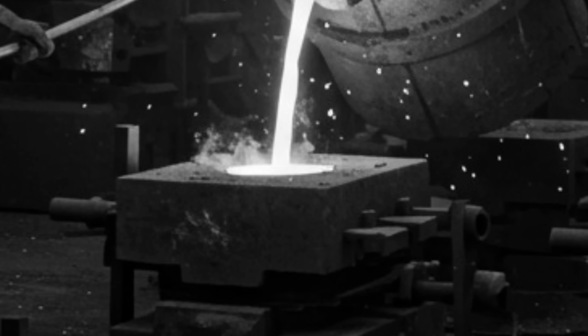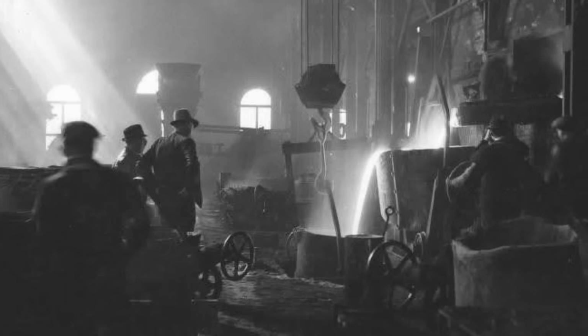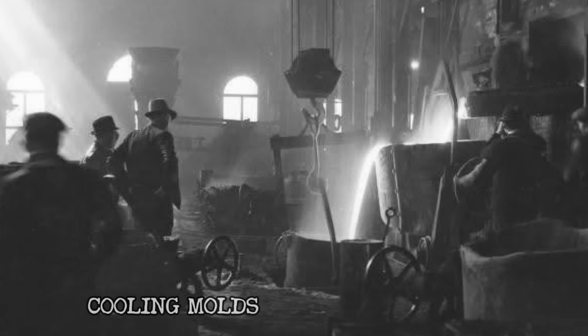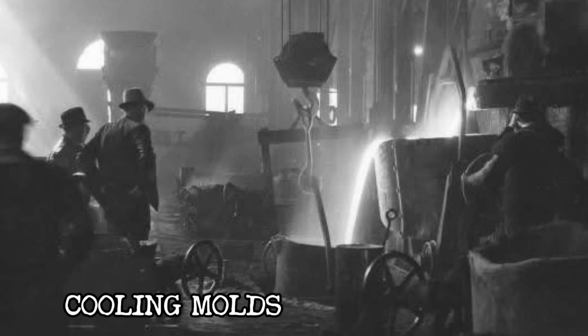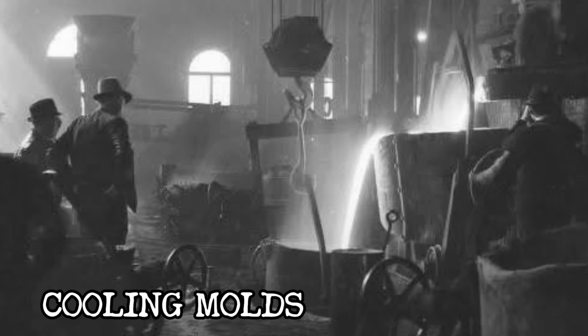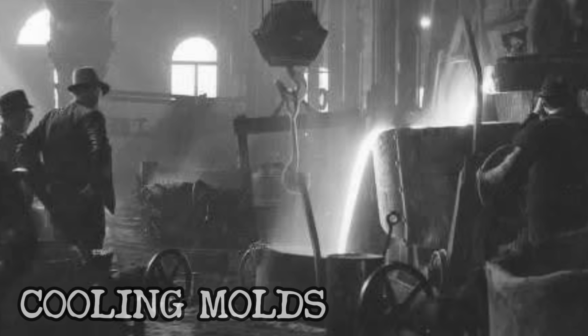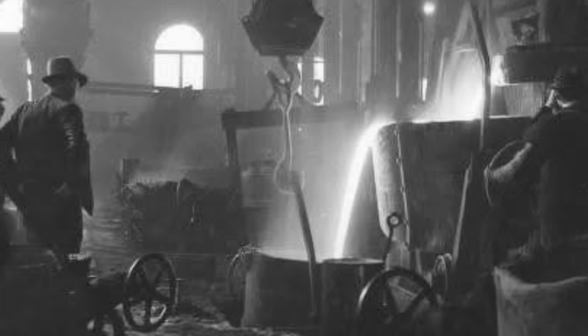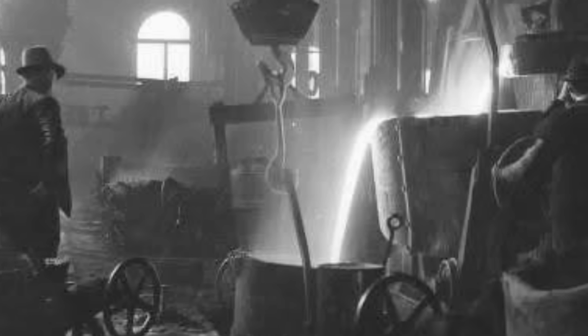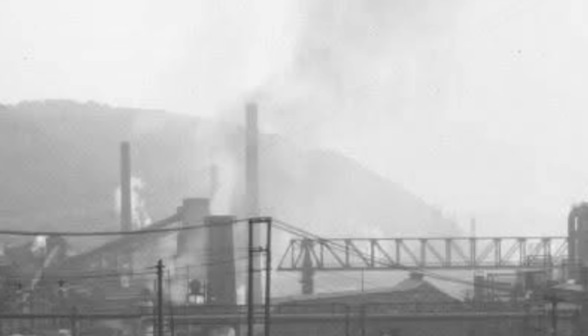Not intentionally, but condensation from the humid Pennsylvania air, water from cooling the molds, spillage from the quench tanks, leaks from overhead pipes, puddles, damp sand used in the mold-making process, moisture everywhere, and everyone in the foundry knows the rule, the iron law of molten metalwork. Water and molten steel don't mix. When water hits molten steel, or when molten steel hits water, the water doesn't just boil. It explodes. Instantaneous conversion to steam.